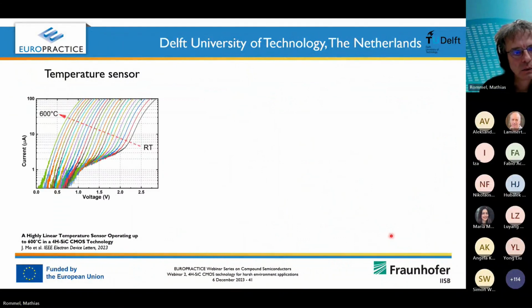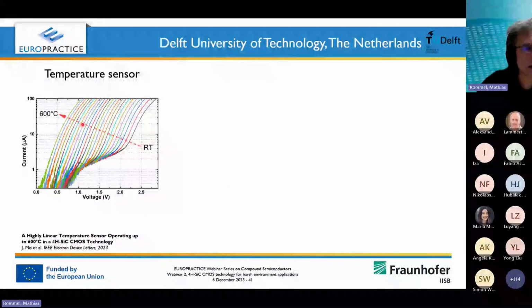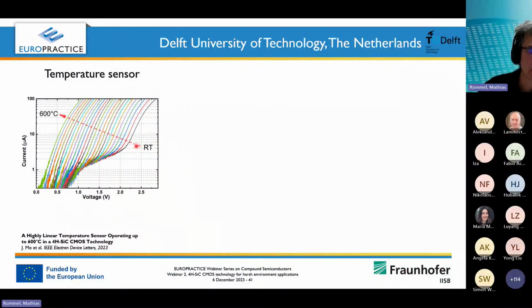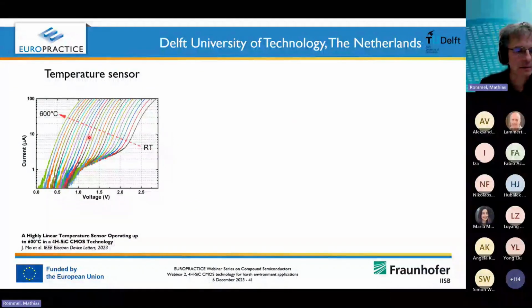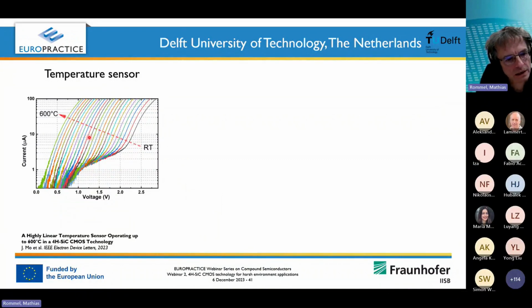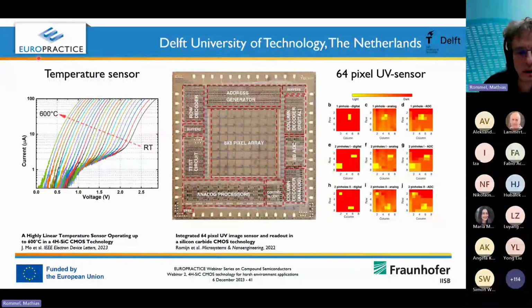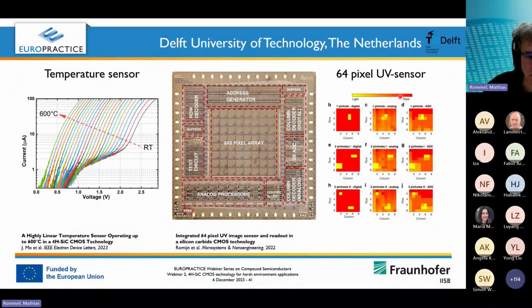Temperature sensors are one of the most important sensors we also want to realize. They realized a temperature sensor with a relatively constant change of its characteristics over temperature, and here really from room temperature up to 600 degrees C, which we also aim at as the maximum operating temperature for our technology. And that was quite linear behavior, so that's something you can realize with this technology. But you can go, of course, much more complex. And this is maybe the nice example of what you can achieve here.